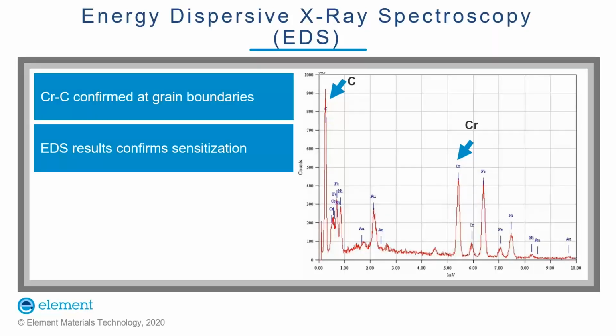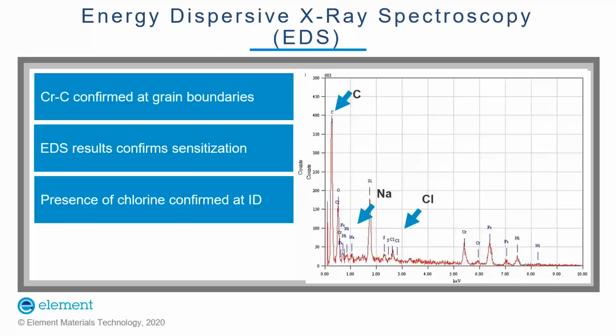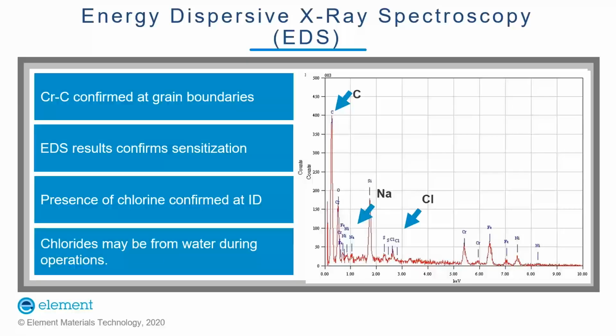Presence of chlorine was also observed in several locations, and one of the locations was the ID. We also did different analysis, and the non-failed tube also confirmed the presence of chlorine. The chlorine may have originated from water used during operation, and that might have made the material prone to stress corrosion cracking.